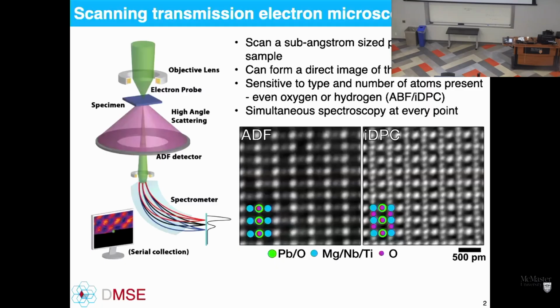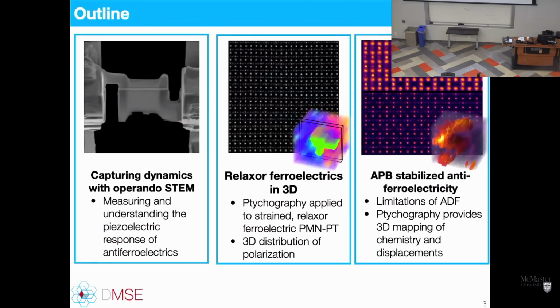But about 10 years ago, a technique, integrated differential phase contrast, came on the scene in terms of what people were able to do routinely. And this allowed us to retrieve the information about oxygen and its position, even hydrogen in some cases, and build up these images. I'll show some downsides to this technique in a minute, but essentially aberrations of the microscope and sample tilt make this technique extremely sensitive to those factors, and as a consequence, they don't tell you everything about the material and polarization specifically. It's not accurate. So that's just to give you a background of the general area of STEM.